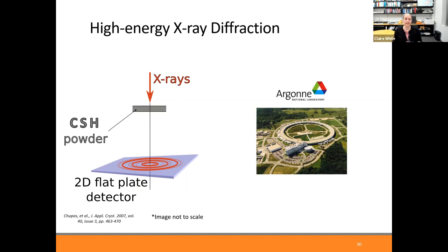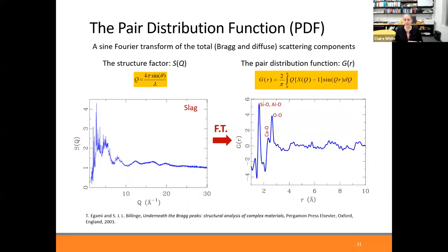It also means that, depending on the energy of the X-rays, you can get different 2 theta coverage of your X-ray diffraction pattern, which means that you can do Fourier transforms of your diffraction data and look at the data in real space. And so that's what's shown on this slide, to actually get the pair distribution function from diffraction data. This is neutron data, and on the x-axis is momentum transfer. It's related to 2 theta, the scattering angle, and the y-axis is intensity.